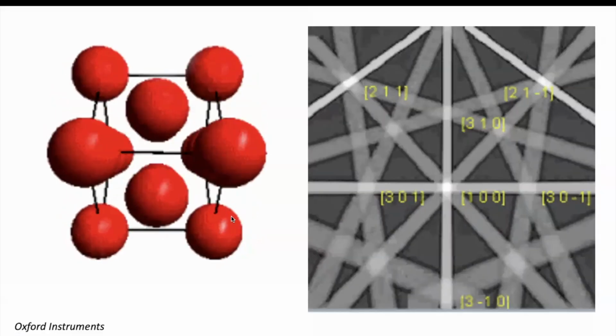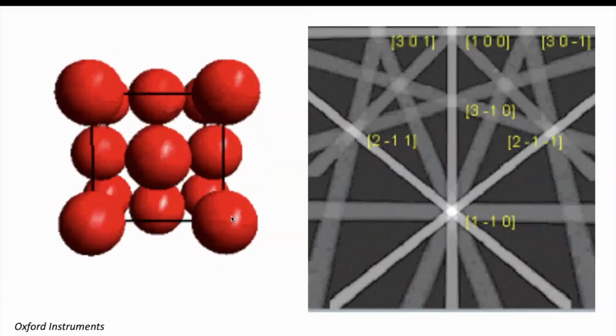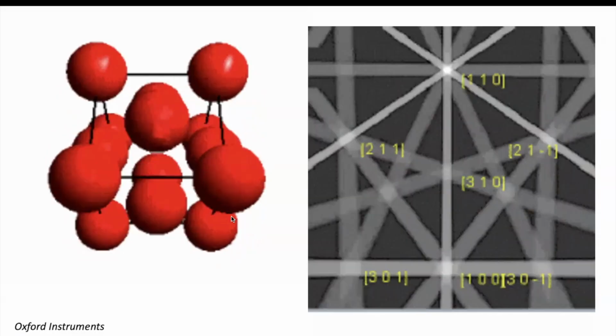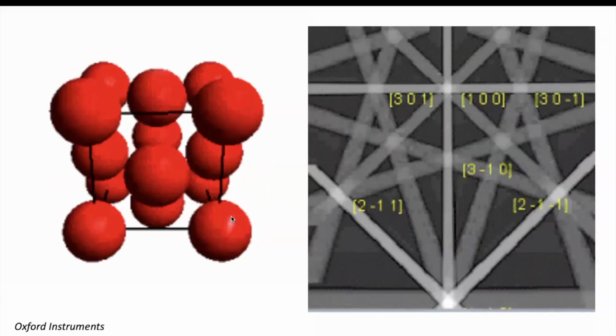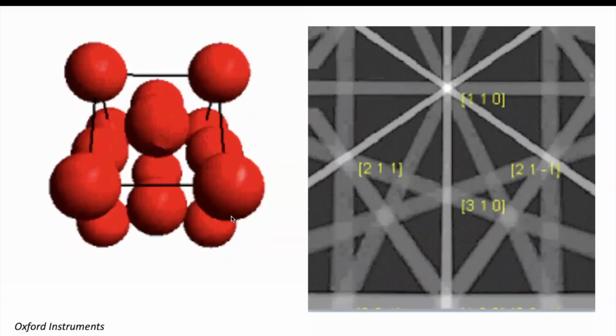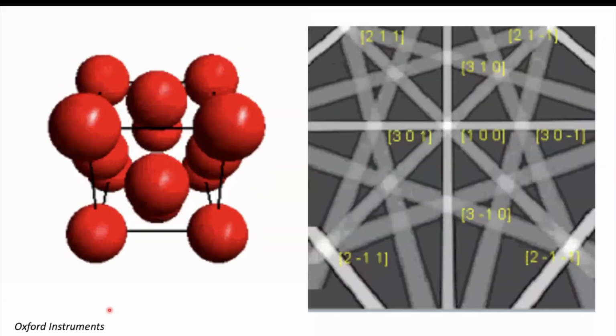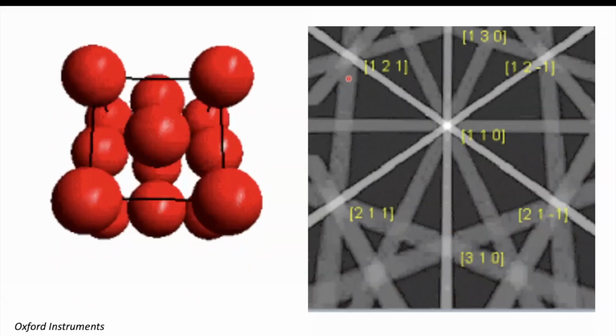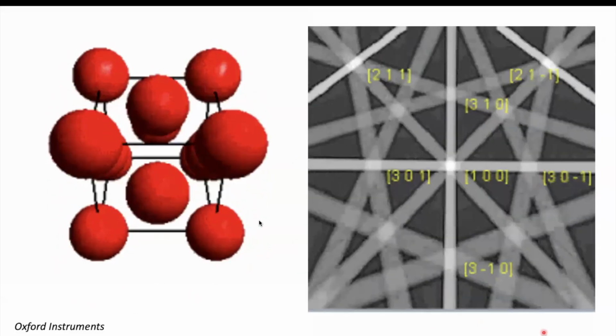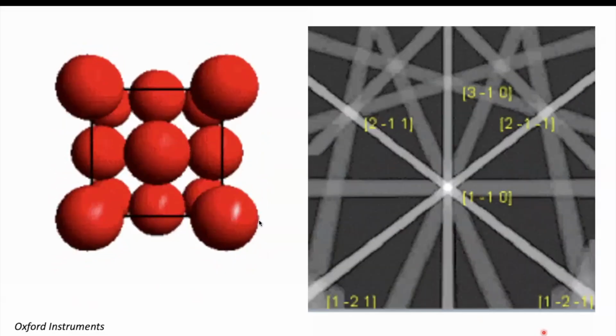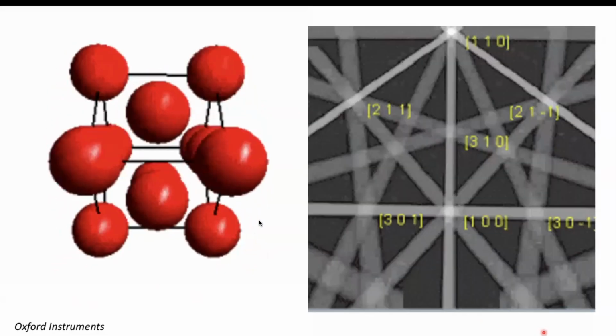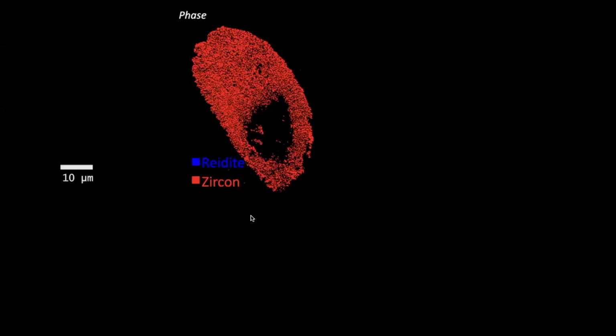So if you haven't done EBSD, it's a technique where you can do diffraction in a scanning electron microscope. You don't have to thin something enough that it's electron transparent. And as the crystal moves, you get specific Kikuchi line diffraction. And then we can just have software map it for you. So that's what I did with these two grains.